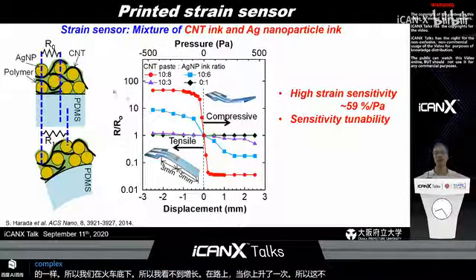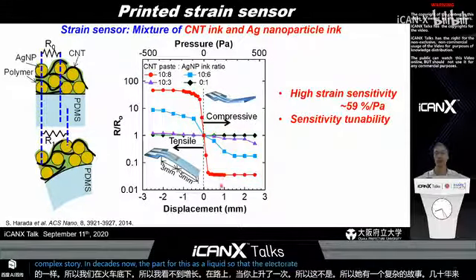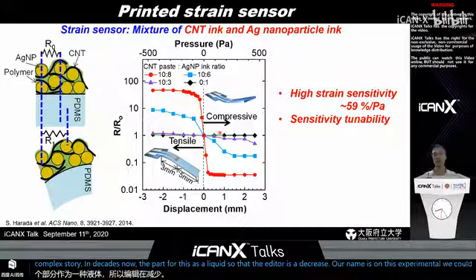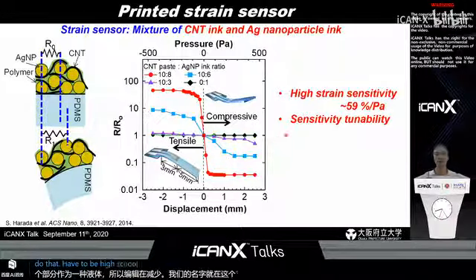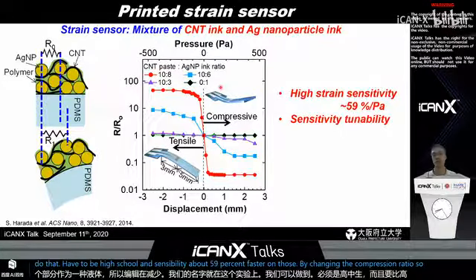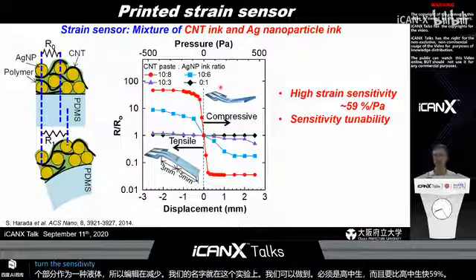In that case, nanoparticle distance is decreased, so that electrical resistance is decreased. Based on this experiment, we could realize relatively high strain sensitivity, about 59% resistance change per Pascal. And by changing the composition ratio, we can also tune the sensitivity of the strain sensors without changing the device design. Then I want to move to the printed temperature sensors.